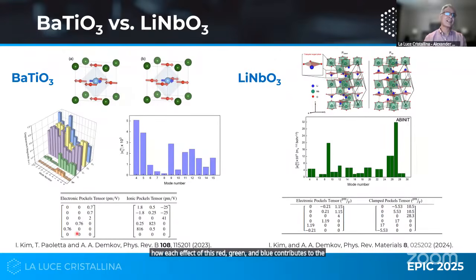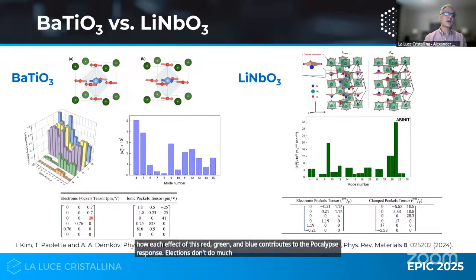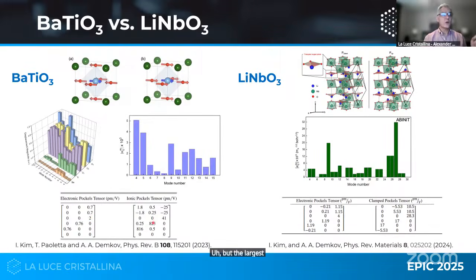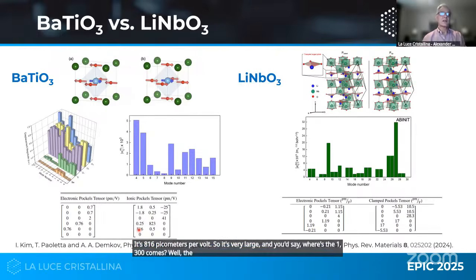Pockels response, electrons don't do much. So the largest one, R33 electronic, is 2 picometers per volt. But the largest optical phonon one is 800. That's R42. It's 816 picometers per volt. So it's very large. And you'd say, where does the 1,300 come from? Well, the other 600 comes from strain.